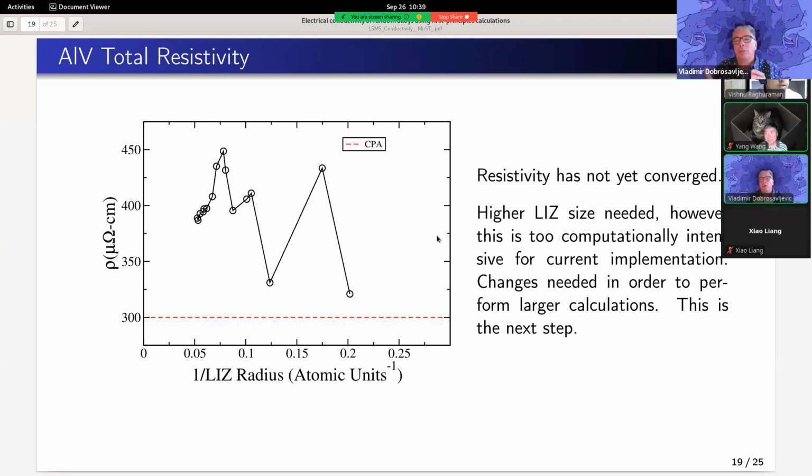But you know, the reason maybe why this is so off from effective medium theory is that outside your cluster, you're really not treating it in an optimum way, right? Whereas CPA does put an optimum medium. So if one actually did put an effective medium, like a CPA effective medium outside the cluster, then probably convergence would be much faster.